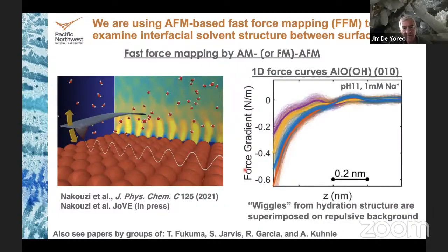This is a plot of the force gradient versus distance that the cantilever sees. This is a 2 angstrom scale bar. And what you see is a typical pattern, which is a decreasing value. And that is reflective of a repulsive term between the tip and the surface that has to do with nanohydrodynamics, sort of a competition between nanohydrodynamics and van der Waals attraction.